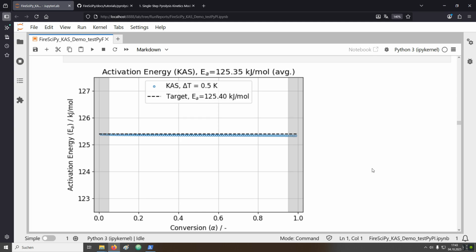The gray areas at the beginning and the end of the plot highlight the initial and final 5% of the conversion. Remember, I mentioned earlier that a common range to assess the activation energy lies between 5 and 95%. This is primarily driven by the quality of the data, but also, or maybe even more important, the limitations of the experiments. This will become clearer when we are talking about how to process the experimental data in the next video. Regardless, I personally would suggest for you to compute the data over the full range and then highlight the areas that you would like to cut off, similar as it is done here. This will provide more transparency to the readers of your work.